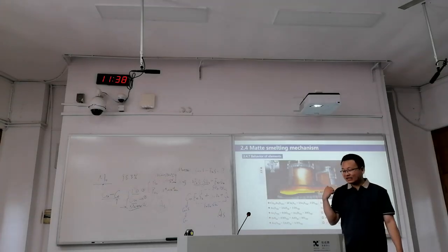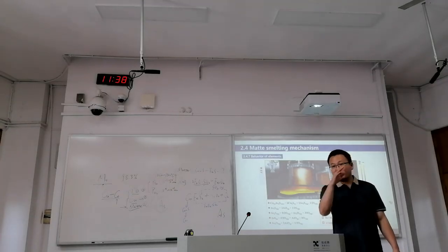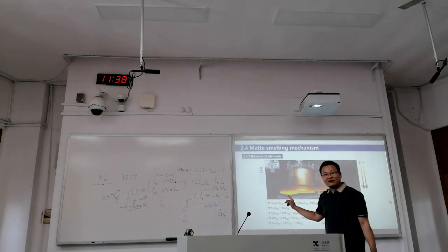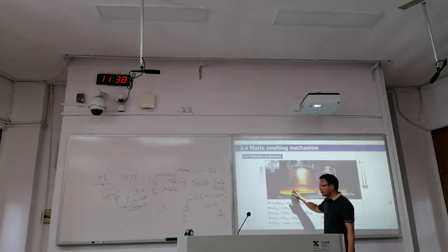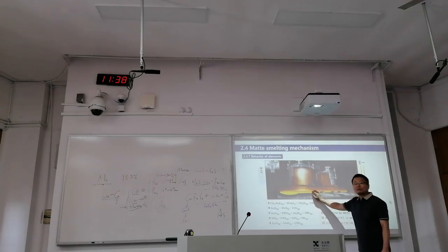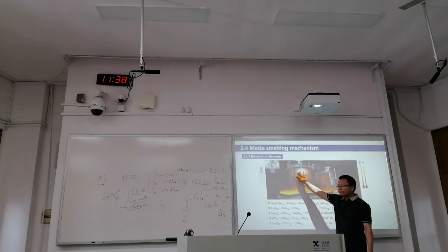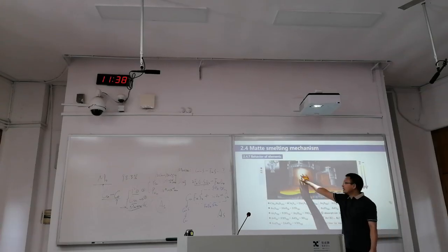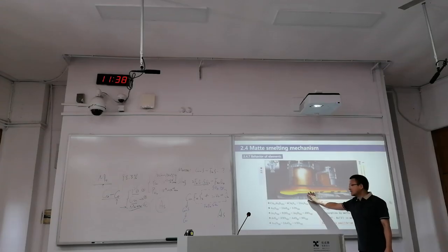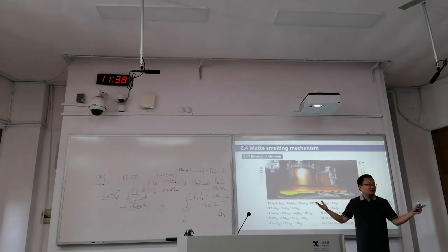If arsenic cannot be solved, the copper process will be stopped. And for flash smelting, we are having a slag phase with very good dissolving for capturing arsenic in the tailings. And nowadays, we can allocate more than 60% of the arsenic in the slag. So this is very nice.